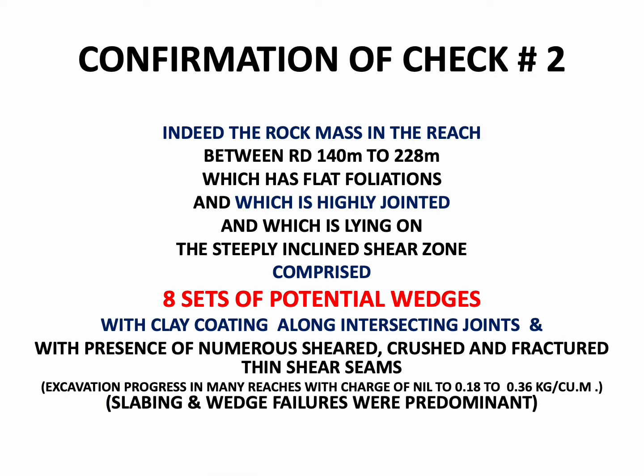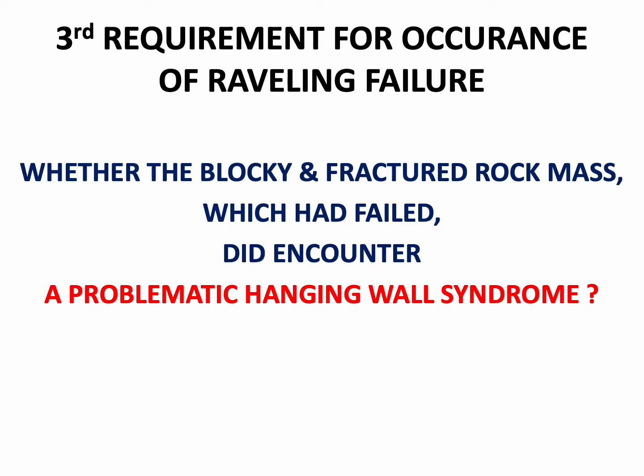So it confirms the second check also, that indeed the rock mass in the reach between RD 140 to 228 meter, which has flat foliations and which is highly jointed and which is lying on that steeply inclined shear zone, comprised 8 sets of potential wedges with clay coating along intersecting joints and with presence of numerous sheared, crushed and fractured thin shear seams, and they had their orientations as steep to lie within the friction angle. Therefore, the slabbing and wedge failures were predominant. So the second check is also confirmed.